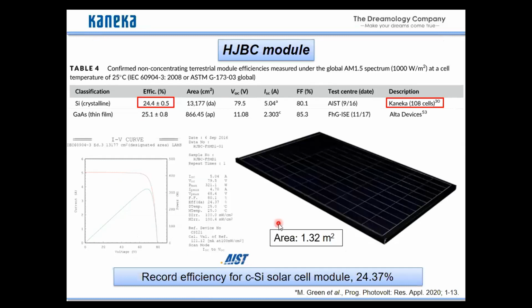And we made the module also with the heterojunction back contact cells. That efficiency was 24.4% with the area of 1.32 square meter. This is also record module efficiency on crystalline silicon technology, so it is noted on the efficiency table. This also like this. And you can find another record efficiency of 25.1% on gallium arsenide based module, which is more expensive technology. Actually, our technology is getting close to them.